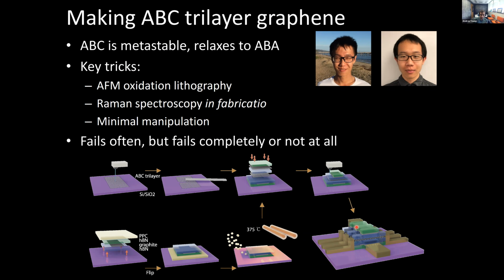Okay, now the process of actually doing the experiment is not so trivial in ABC as compared to, for example, Bernal bilayer graphene, because ABC is not the ground state configuration of graphite. It's metastable and, generally speaking, will relax to an ABA stacking without a number of tricks. So to give you an idea of how we actually make these samples, it's true that if you just exfoliate graphene, the same way that everybody who studies high quality graphene will make it, you start from graphite and you exfoliate it onto a silicon substrate where you can look at it. You can certainly identify 3-layer flakes, and then using Raman spectroscopy, you can see that something like 5% of the total area of trilayer graphene flakes will be in this rhombohedral stacking order. And those can be large. You can even find 100 square micron flakes that happen to all be ABC, but it's not a stable configuration.